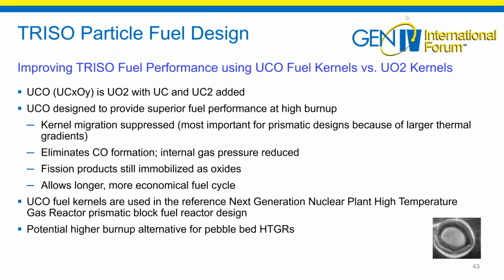We have most of the failures, and we've published this with the AGR-1 data and the pizza pie analysis. Most of the interesting things we saw going into the kernel were buffers cracking. The issue here is if the buffer adheres to the inner pyrolytic carbon as you irradiate, then cracks may form. And as we saw with some of the tomographs, the kernels will bulge out. And if that cracked buffer has fission products that go right against the inner pyrolytic carbon layer, that is usually one type of failure. The other type of failure that we've seen is, and they actually don't fail, the buffer tears away mostly uniformly. Okay.